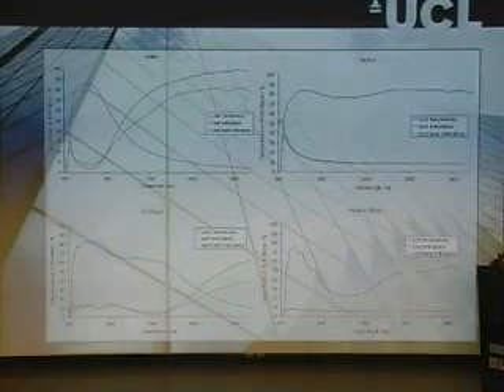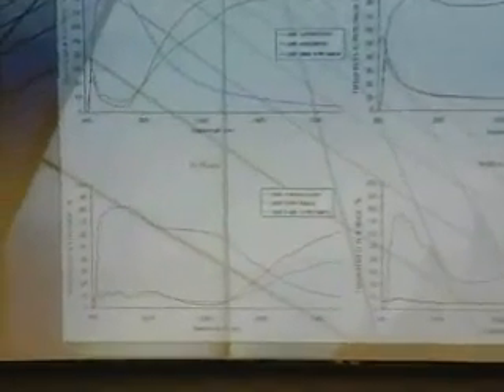The top left is our sputtered coating. You can see the reflectance, the red line. It's very high in the near infrared. It basically gets rid of all of the solar radiation before it is allowed to enter the building. Bottom left is a low E coating. So you allow a large amount of visible and near infrared light through, but you're starting to see the reflectance creep up in the far infrared, and the far infrared extends right along to up to 50 microns, where the reflectivity is about 85%.